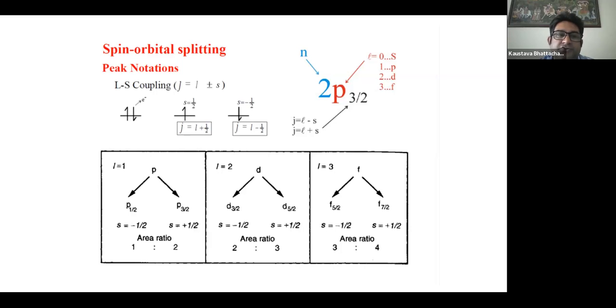But the area ratio for that particular element should be 2:1, and also the splitting parameter should be fixed for that particular element. Then only can we consider it as the element we are considering. Equivalently, for the d orbital, the area ratio we can understand as 2j plus 1 for both of them. So that will be 6/4, that is, they should be in the ratio of 3:2. And for f, the 7/2 to 5/2 ratio should be 4/3.